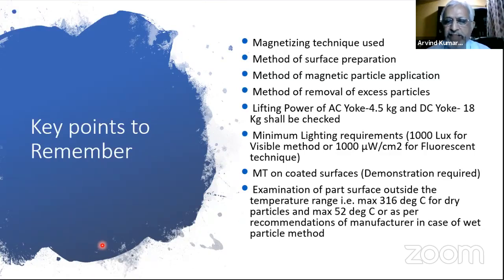Examination of the parts. Generally, dry particles you can use up to 316 degrees centigrade, because they are basically metallic iron particles, so you can use them up to high temperatures. Whereas for wet particles, the recommendation is generally up to 52 degrees centigrade, because they are in a liquid which is volatile, and sometimes kerosene and things like that are used. We have to make sure that whatever the manufacturer's recommendations are, we restrict the temperature as recommended by the manufacturer for the wet particle method. But it is definitely not advisable to go beyond 52 degrees.